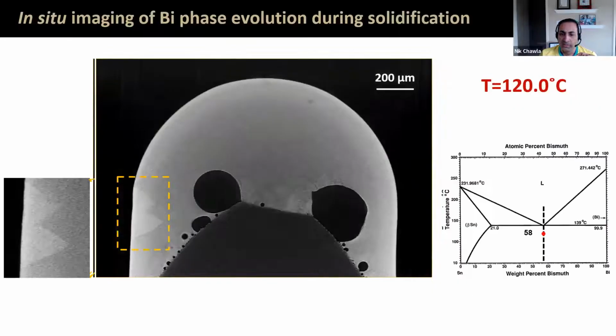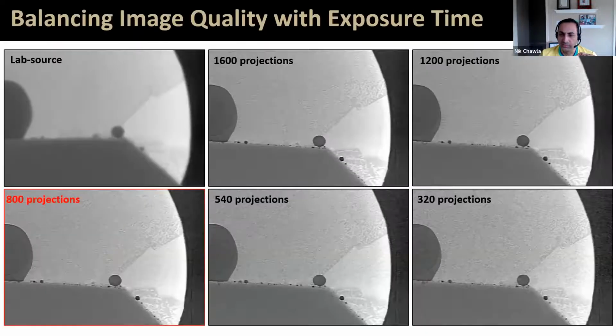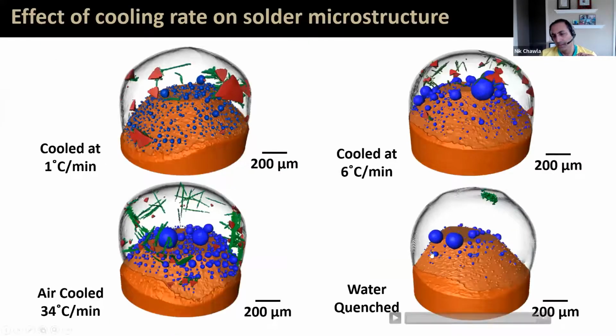In the water quench case, we don't see any particles here. At the bottom right, we only see porosity. And the reason is that we have not given enough time for the bismuth to precipitate and diffuse out of the liquid. So it's still there, but we can't resolve it because it's actually solid solution. It's trapped inside of the tin. It doesn't precipitate out.